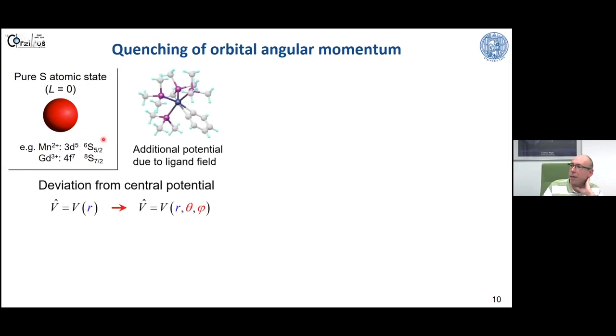So we also have to look at other cases where we can work with a nearly quenched orbital angular momentum. And this is, for example, if we work in a ligand field. If we put an ion inside a ligand field, we have an additional potential due to the ligands. And this causes a deviation from our central potential. The central potential is what we introduced with the hydrogen atom, where we have a potential which is only a function of the distance from the electron to the nucleus. And now we have another term, which is now angular dependent, because each ligand, of course, has a certain orientation around the ion.